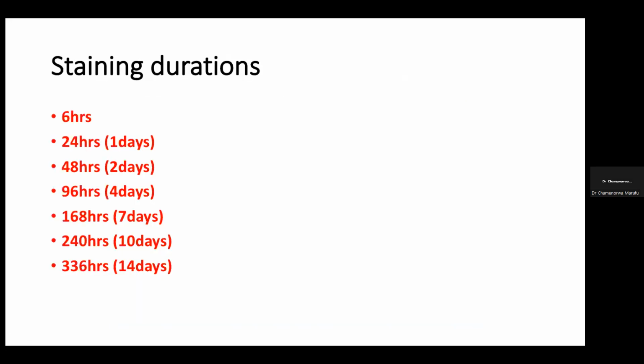in the staining solution. And then the staining durations were those indicated there, which is 6 hours, 24 hours, 2 days, 4 days, 7 days, 10 days, and 14 days. And initially we measured the color before we started the staining process to get baseline measurements. And then at each interval, we would use a toothbrush to clean each specimen for around 30 seconds, and then we would rinse it with distilled water.